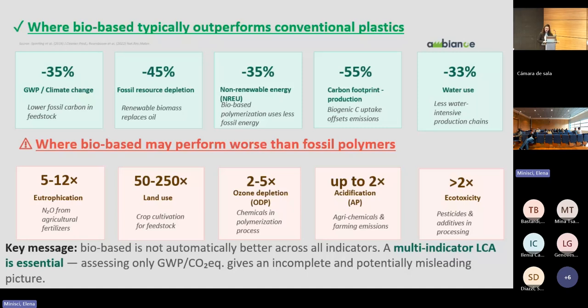We have, for example, the eutrophication that performs from 5 to 12 times higher than conventional plastic. The land use from 50 to 250 times higher. The ozone depletion, the acidification, the ecotoxicity. So what are the reasons behind this worse performance of the materials? We have, for example, the use of fertilizers during the production of the crop, the chemicals and additives that are used during the polymerization phase, and also during the production of the final material in order to guarantee the same characteristics as the conventional plastic.